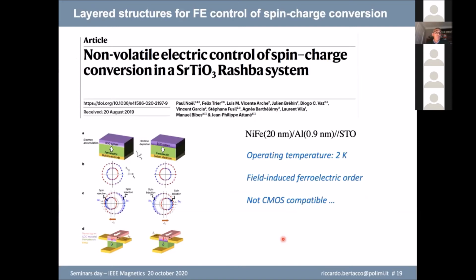And in this very well-known paper by the French group in Paris, they found that if you realize a layer structure in which you have a ferroelectric layer, in this case it was strontium titanate at very low temperature after application of the field, in connection to a two-dimensional electron gas, which is from the interface with the metallic layer, you can really observe a Rashba effect, which determines a change in the spin to charge conversion when you change the polarization in the ferroelectric layer. So it's a layered system in which you exploit the two-dimensional electron gas in proximity to